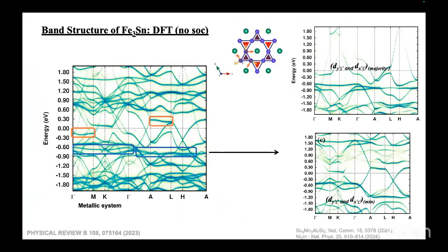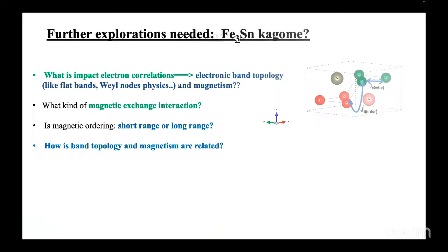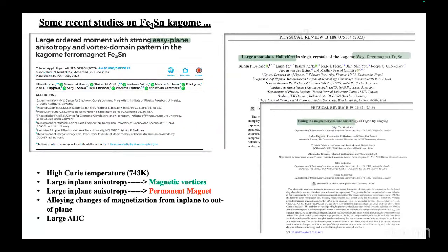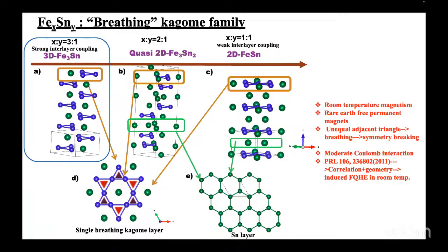So based on the literature, in the 2D FeSn system, people have seen flat bands completely over the Brillouin zone because it is near the two-dimensional limit. And in the quasi-2D, there is the presence of Dirac cones apart from the flat bands. So that is also very interesting as we go to the two-dimensionality of the system.